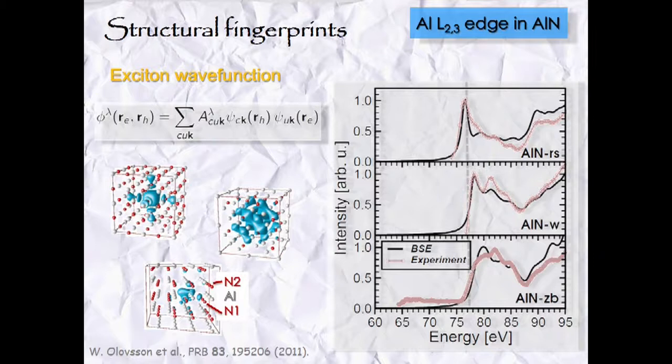So just want to confirm that the positive charge is fairly localized, just at the hole, because this is the state you have taken out. Yes, just at the hole. For valence states, you can do the opposite. You can fix the electron and see how delocalized the hole is. But for core states, this is not needed. So in that sense, core spectroscopy is in a better position to get direct insight into the shape of the electron hole pair.